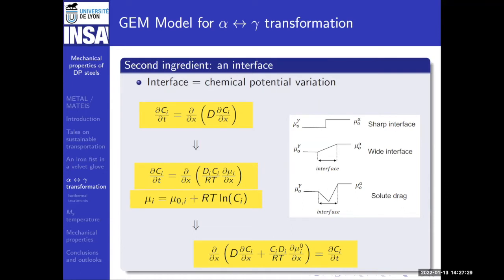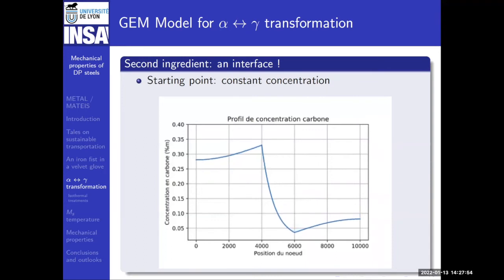If you have, for example, austenite on this side and ferrite on this side, the chemical potential is a step function like that. We can have an interface which has a certain width, and eventually we can have an interface with this kind of potential well, accounting that solute atoms may prefer to locate at the interface. So once we have included this ingredient, let's see what happens when you start with a constant concentration profile, but with a chemical potential that makes a step. We end up with a concentration which is higher in one phase and lower in another one. If you think of iron-carbon, for example, you know that carbon solubility is much higher in austenite than in ferrite. So that was the second ingredient of the model, the modeling of an interface with two different domains.